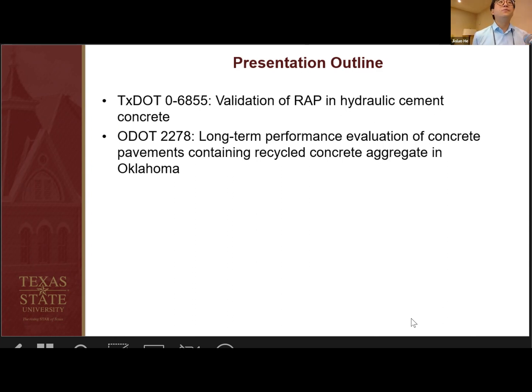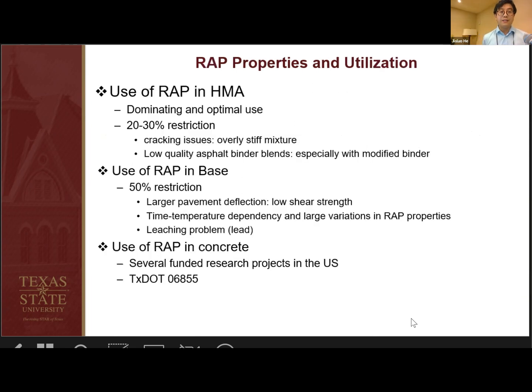The second one is a project we did for Oklahoma DOT. Actually, it was a field investigation. We looked at a concrete pavement section made with 100% RCA as coarse aggregate, and we evaluated the field performance. So the first project was from Texas DOT and using RAP in concrete.